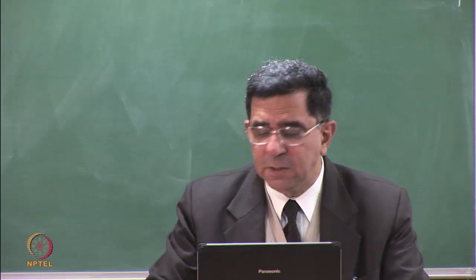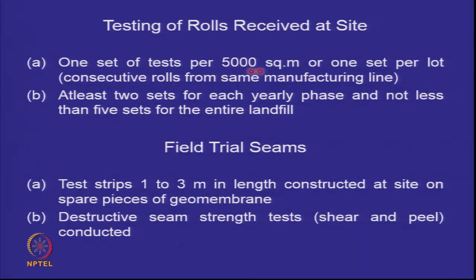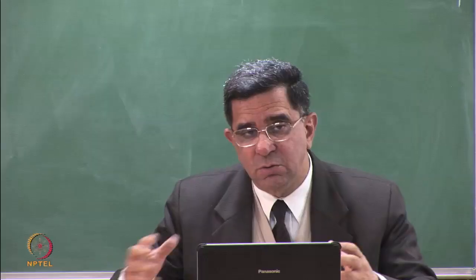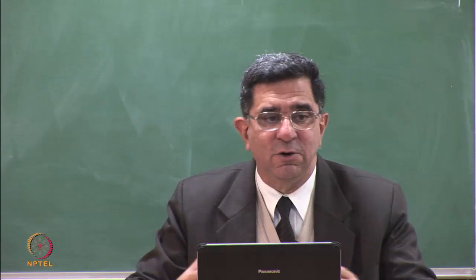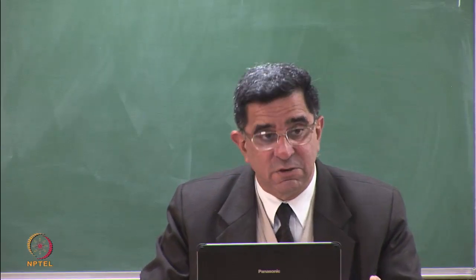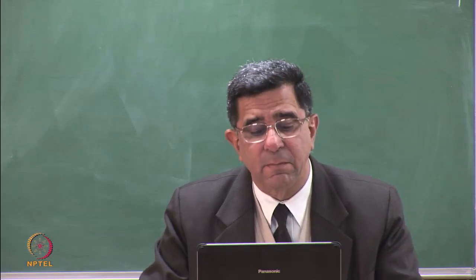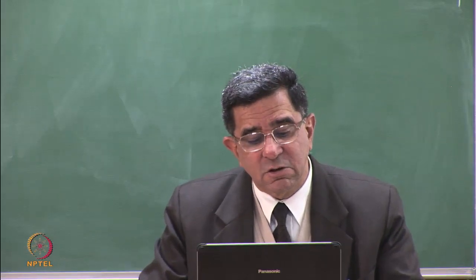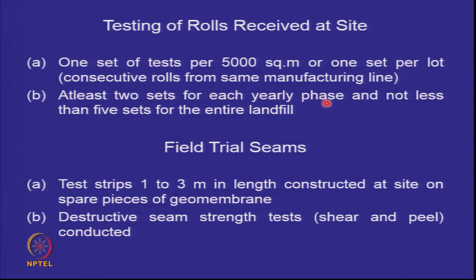So typically one set of tests per 5,000 square meter is what you do. And one set per lot. I mean, if geomembranes are coming to you in different lots, then you do one set per lot, which may be less than 5,000 square meter. But at least two sets for each yearly phase, and not less than five sets for the entire landfill.